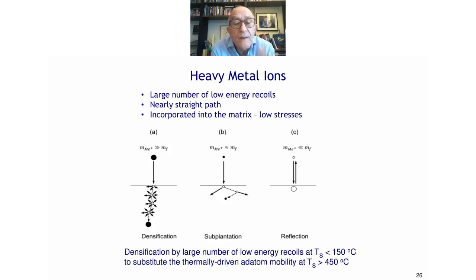In the middle section, when the masses of the ions and the target are similar, we have cascades that are not dense and high energy recoils because of the close mass match. If we go to the left column, very heavy ions, first of all, they cannot be deflected by the light atoms, so they go a straight path, and they produce a lot of low energy recoils, which we thought could be used for densification at low temperatures to substitute the thermally driven atom mobility at higher temperature and the traditional ion-assisted growth by, let's say, argon or nitrogen irradiation. So the first experiment, next slide.